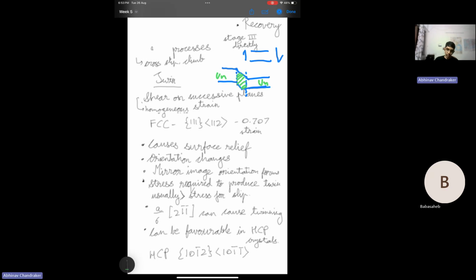So all the atoms move by a very specific value in the twin region, and there's a uniform strain. For example, in FCC it is 0.707, which is quite high. This is in the twin region, and there are multiple characteristics of twins which are all different from that of slip. They are very different mechanisms. Twins are also associated with very specific planes. So, for example, in FCC, it occurs in the 111 plane and in the 112 direction.